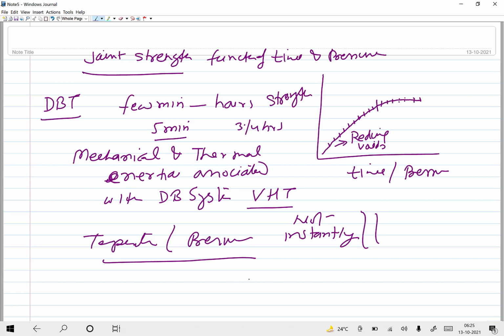Like if you want a temperature of 600 degrees centigrade, it may take a long time, maybe 2 hours or 1 hour initially to reach, depending upon the heating rate and the system capabilities. Likewise, if you want to apply the pressure and control it within certain limits, the system will take some time to reach the desired loading in order to achieve the desired pressure. So it always takes some time to reach the set temperature and set pressure.